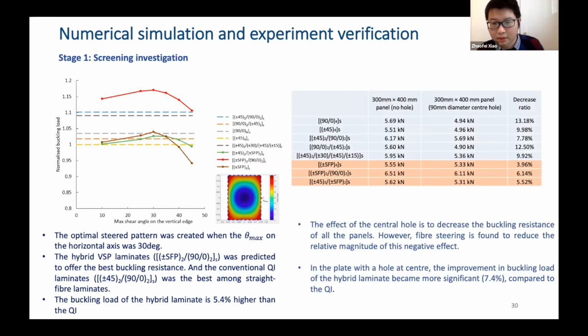And if we look at the details of the buckling data on the two panels, one with the hole and one without the hole, we can say that having the hole in the middle decreases the buckling load of all the panels. However, if we have the steered fiber laminates in the composites, we reduced the negative effect from 10% in the straight fiber laminate to only about 5%. And if we also compare the buckling load of the best hybrid laminates and the QI laminates, the improvement ratio becomes more significant at 7.4%, compared to 5.4% previously.